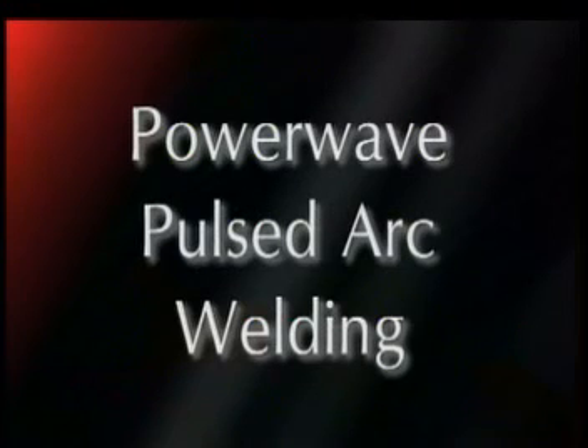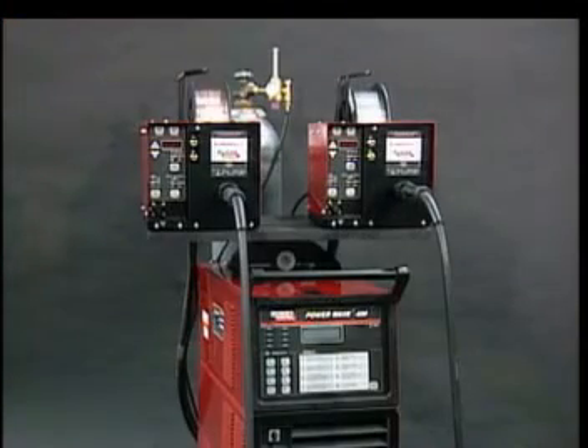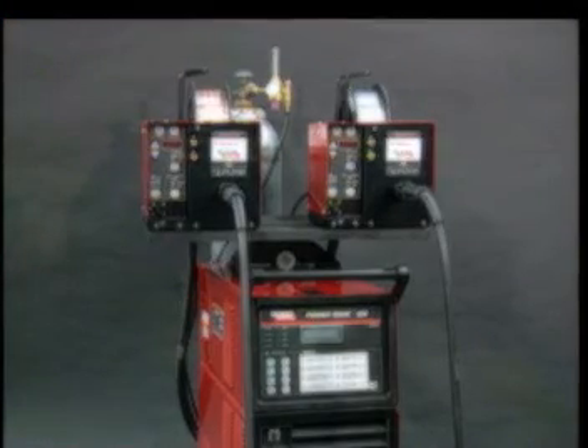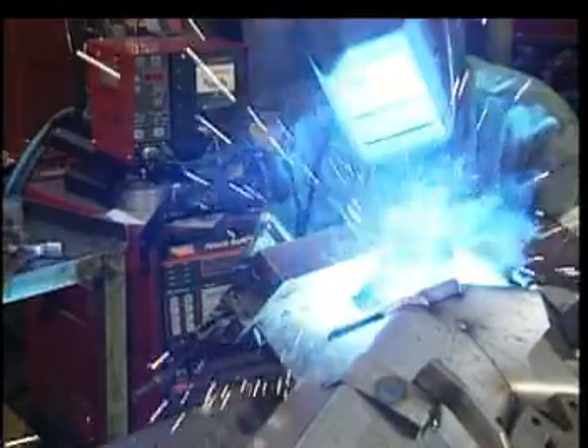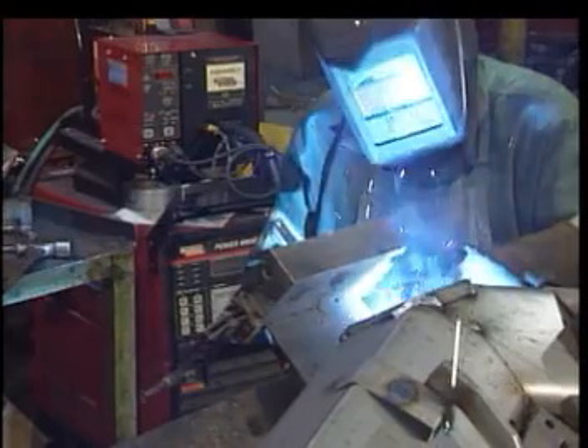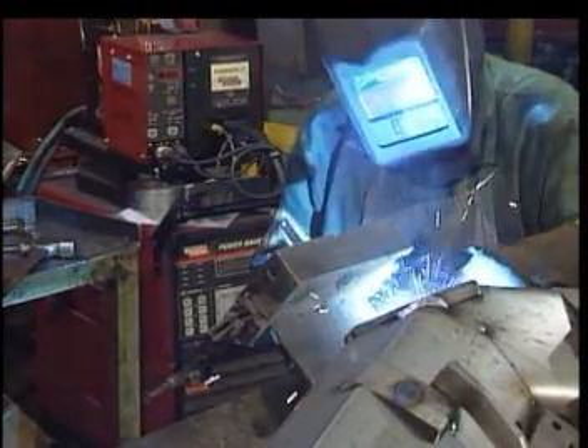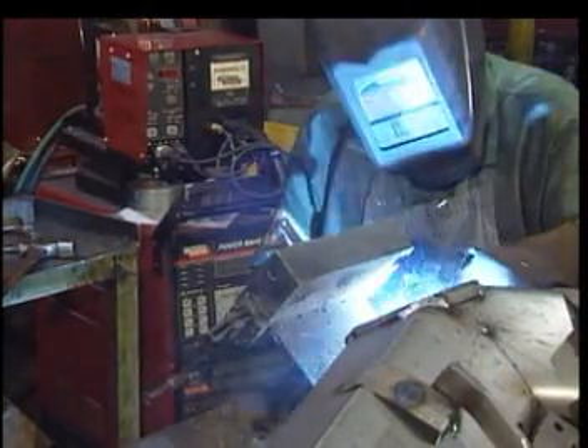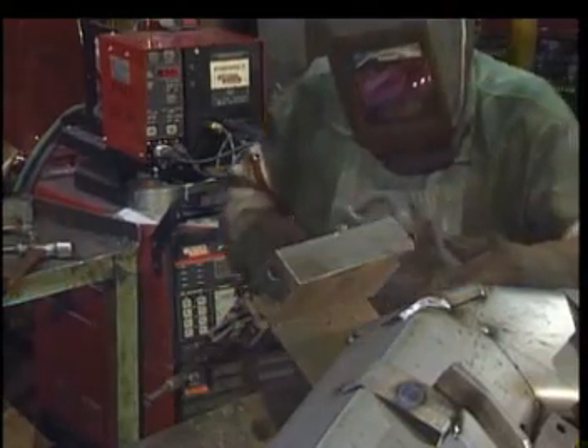We would have a precise control of the arc through a very broad wire feed speed range. That is the major benefit of using the Lincoln PowerWave pulsed arc welding process. The process allows wire feed speeds ranging from 50 to 1200 inches per minute, and it's virtually spatter-free across the entire range. With precise control of arc dynamics, the PowerWave can be used as a fast freeze process at high travel speeds, or it can be run as a high deposition rate fast fill process.